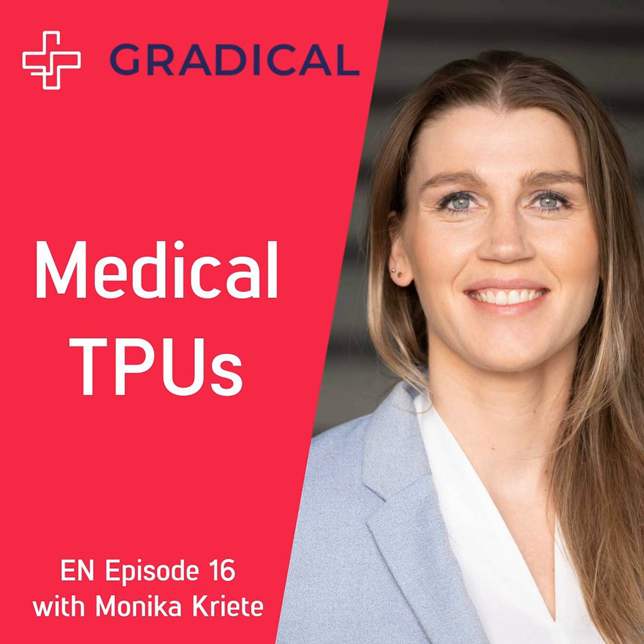There are certain ways how you can test for it. I would also say in that regard, we are happy to guide a bit on how you can test for those, because some test methods might show a false result. For example, if you do an IR analysis, it might show up as an isocyanate, whereas it's actually just an end group of a longer chain, which can lead to a false result in thinking there might be free isocyanates, but it's in the end just the end group of the chain. And for other methods, there are also things to consider to make sure that you're not creating free isocyanates while measuring. So these are things where we are really happy to help or guide our customers if they have these concerns or are testing for it, because it's not as straightforward as you might think to really test for those free isocyanates.